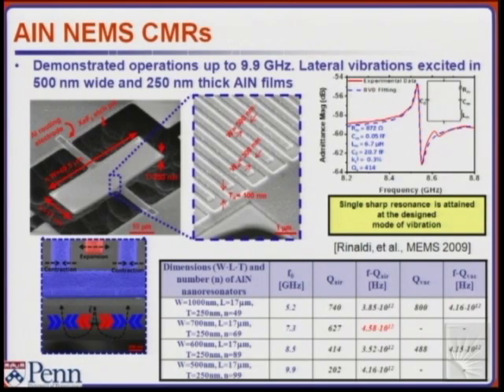And with pattern features, this feature was done with E-beam lithography. We don't have a stepper that has this kind of capabilities, but we use basically a last step by E-beam, right? I mean, in a CMOS foundry, making 300 nanometer is not a problem, right? It's not a big deal, but it was for us, so we had to interface the E-beam to the standard stepper.